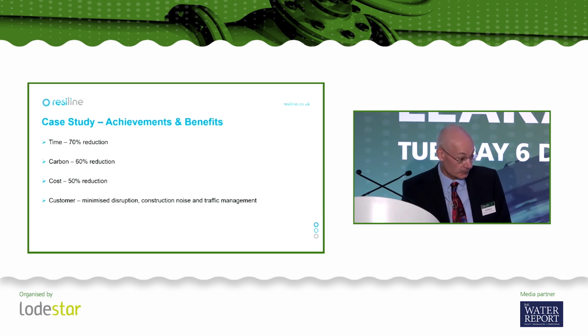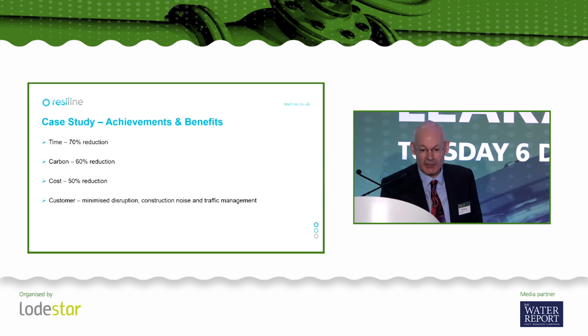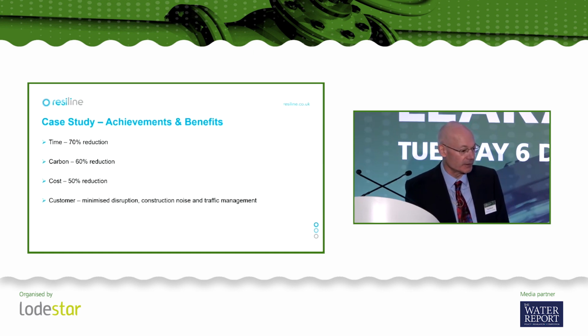So, according to Morrison Water Services, they achieved these benefits in comparison to replacement. Very significant reduction in the time spent on site. A meaningful reduction in carbon and a good reduction in cost. Now, because of the geographically dispersed locations involved, from a cost perspective, I'm pretty sure that scheme wouldn't have been as cost effective as other schemes where you've got a much higher concentration of mains in a smaller geographical area, but still a meaningful reduction in cost. And finally, an enhanced customer experience compared to replacement.